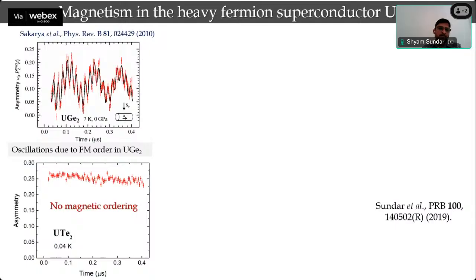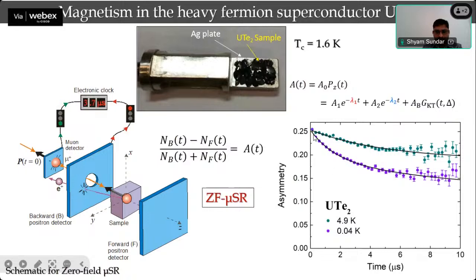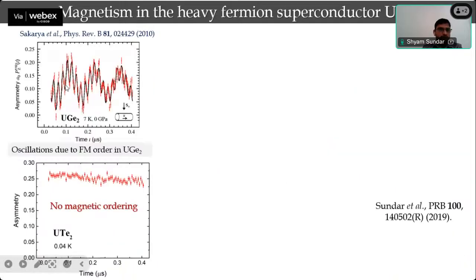So how do we find out if there is a magnetic ordering or not using the muSR measurement? If you have a magnetic ordering, such as in uranium germanium 2, when you plot this data, asymmetry as a function of time, at a very early time, it is supposed to show very clear oscillations. You can fit the data and tell exactly how much magnetic field is associated, and these oscillations are basically the proof that there is a long range magnetic order. And when we did the same measurement in uranium ditelluride, at 40 millikelvin, we did not see any such oscillation.